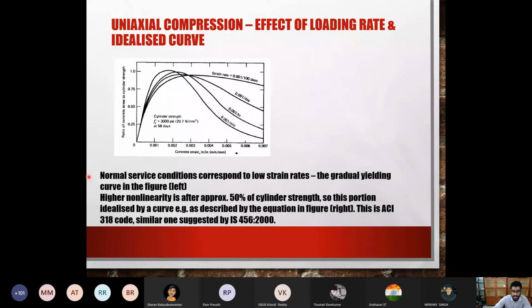So that's why I meant normal service condition means in actual application, like in a building. In a normal service condition, it will correspond to low strain rates like this, so you get the gradual yielding curve. Of course, you see, at least till this 50% of strength, you can have almost a straight line, from zero to a stress to strength ratio of 50%. Beyond 50%, it starts to become a bit parabolic.